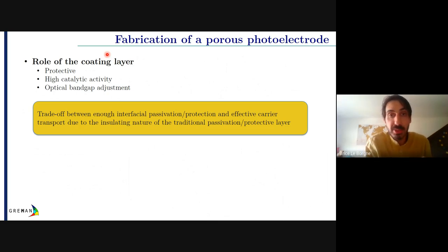to coat porous silicon to try to perform the best possible photoelectrode. So this coating layer should be protective because we know that porous silicon is chemically unstable, as I said at the beginning. So if it's chemically unstable, you need to passivate it. Then, if possible, you should have a high catalytic activity, so you can perform CO2 reduction or at least a chemical reaction at the surface of the porous material. Again, the porous material is also chosen for its high specific surface, and you should be able to perform optical band gap adjustment to perform the desired reaction. I'm not saying I'm gonna manage to do all of this, but we are trying, right?